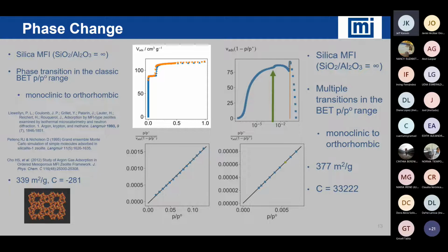Now, the pure silica MFI has been well described and synthesized more than 50 years ago. So this problem has been known for quite a while. It's been discussed in various ways, but a little over a decade ago, it was demonstrated that it's actually a phase change. The material is distorting a small amount during adsorption, and the distortion is only about 1%. So a very minor distortion, yet the quantities adsorbed go from 80 cc's per gram to well over 100 cc's per gram. So you can easily see a 30 to 40% increase in adsorption simply from a minor phase change of the material. So that really has introduced quite a few challenges associated with measuring surface area.